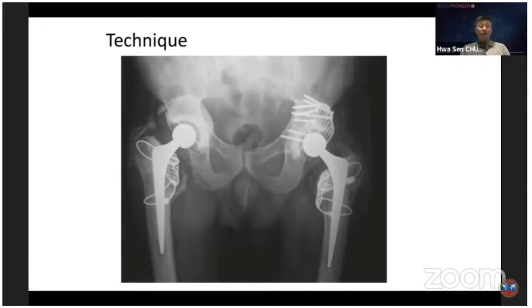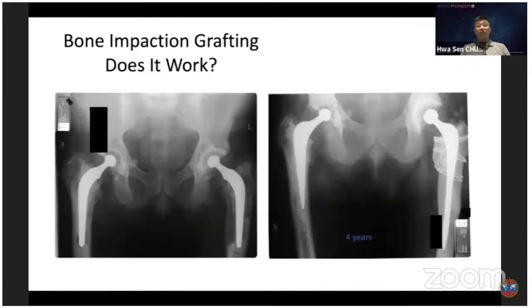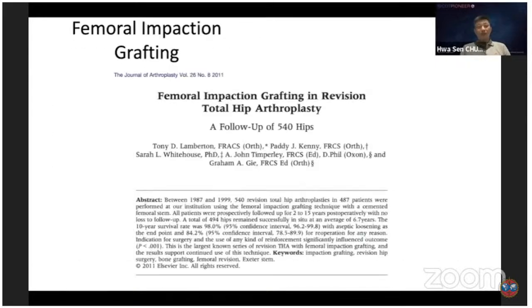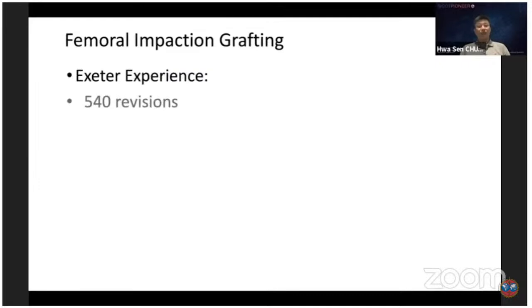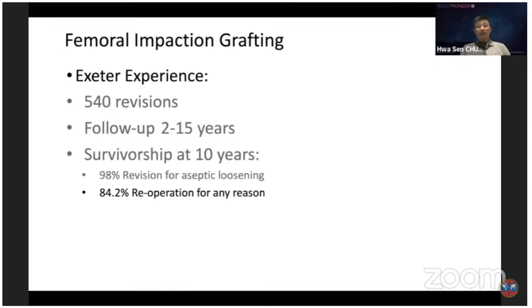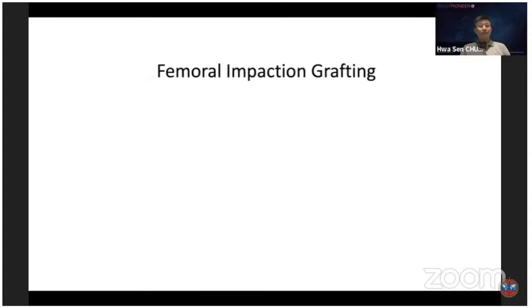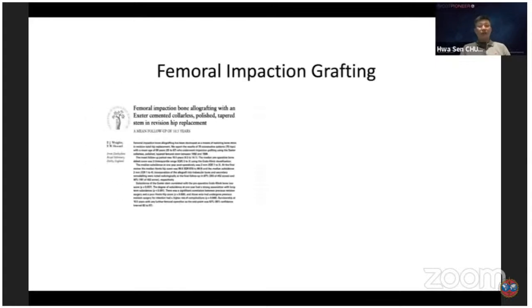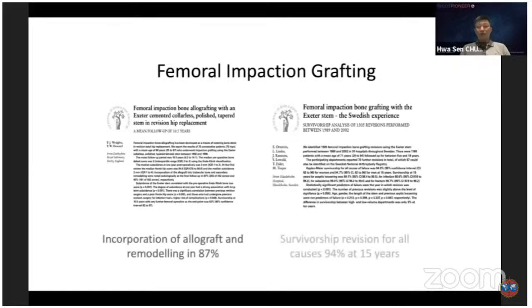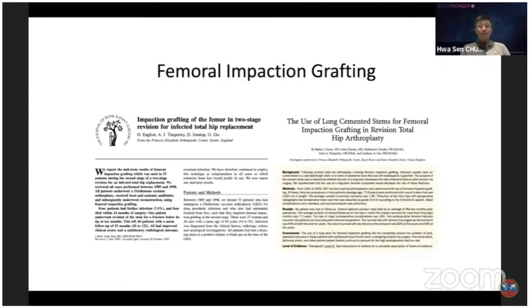Eventually, it turned out to be well incorporated. So the bone graft thing, does it work? We have many studies out there, the long-term one, 540 hips, Exeter's experience, follow-up of 2 to 15 years, survivorship at 10 years of 84%. There is actually much more evidence out there that shows femoral impaction bone grafting does work.